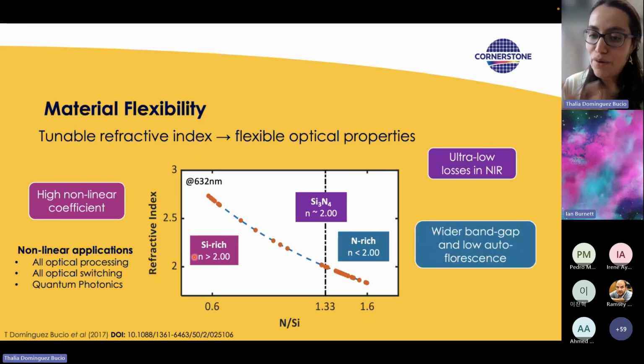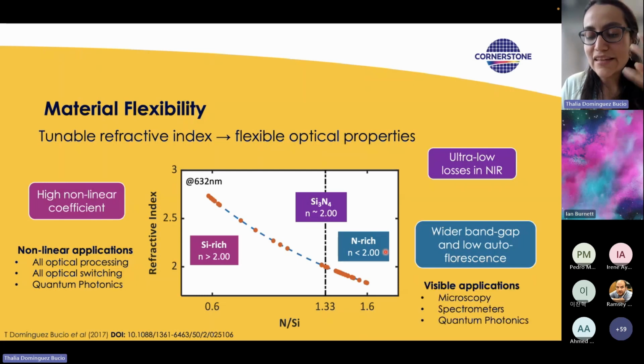Now, if we go to the lower part of the refractive index spectrum, we have nitrogen-rich layers, which have a wider band gap and a low autofluorescence. This is going to make a bit more sense in the next slide, but what it means is that this particular layer is more suitable for visible applications, for metrology, for microscopy, for spectroscopy, and also for quantum photonics.